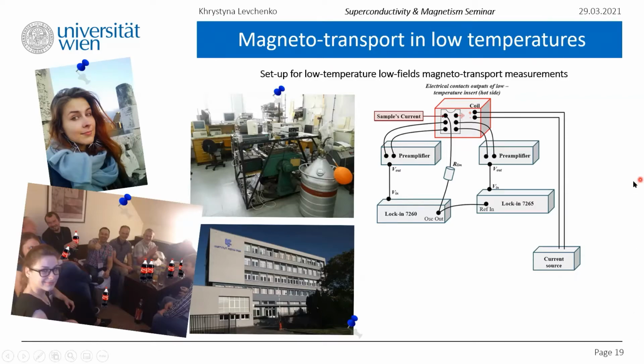And coming back to the topic of our discussion, during our measurements, we were using a low frequency lock-in technique to analyze 2- and 4-point probe longitudinal magnetoresistance and Hall resistance as a function of the applied field. We were applying the field both in plane and out of plane at low temperatures. All measurements were taken in helium, at 4.2 kelvins.